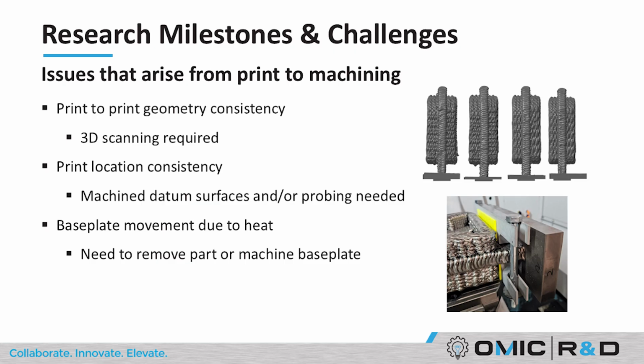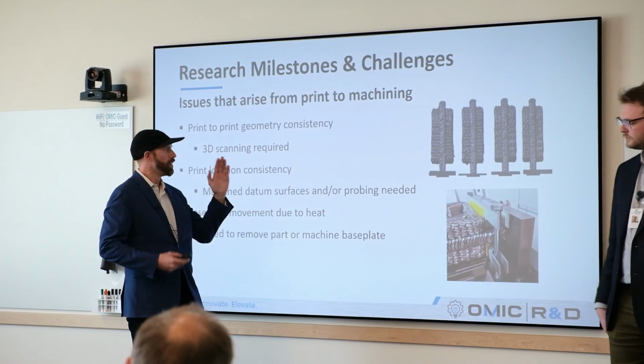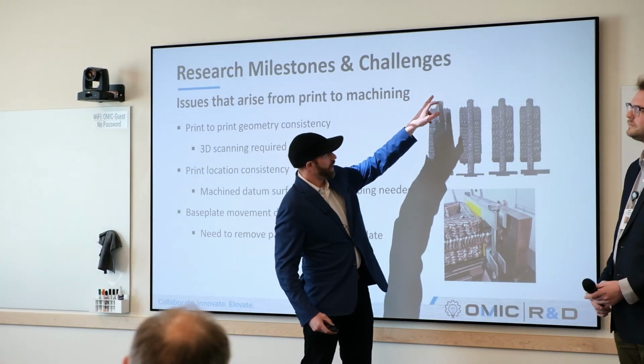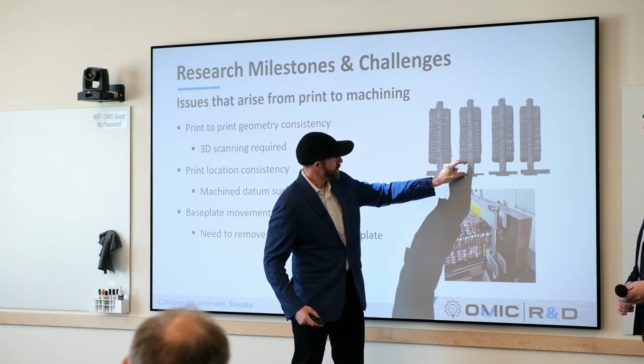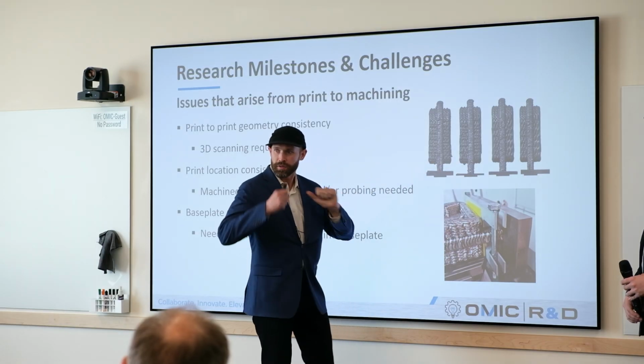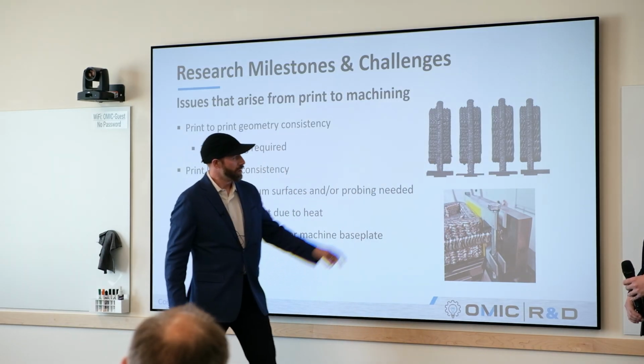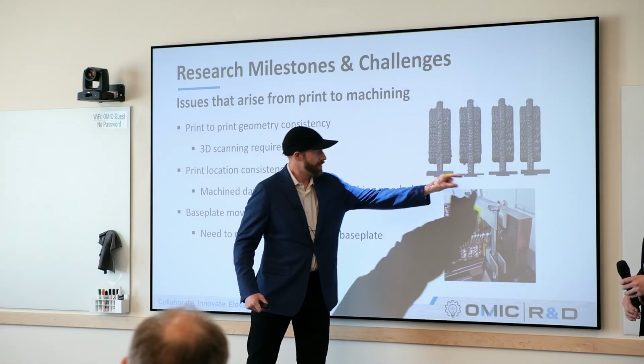So print-to-print geometry consistency, you can kind of see right here, they are different. They're located in different spots in their plates. The ribs can be slightly higher, slightly shorter. Your distance here where you're tabbing out your part to break it off, you have less clearance, more clearance, and then your plate thickness changes.